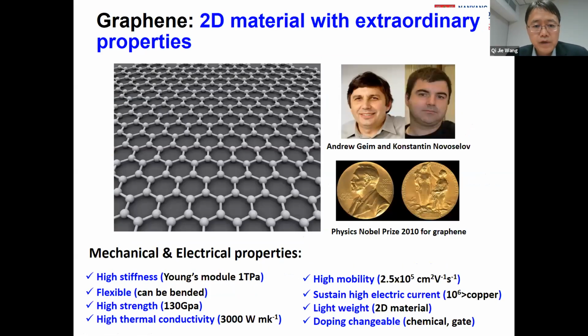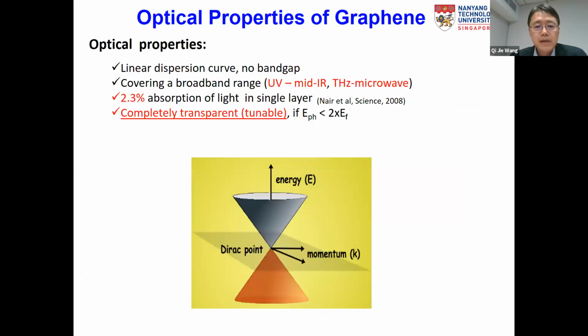Of course, everybody knows graphene. It has several unique properties like high mobility and a linear dispersion curve, so that it can have a broadband photo response from UV up to the terahertz or even microwave region. As shown here, in the mid-infrared region, the absorption coefficient is higher than that in the visible range, which is 2.3%. In the mid-infrared region, because of free carrier absorption, the absorption can reach about 10% for monolayer graphene.